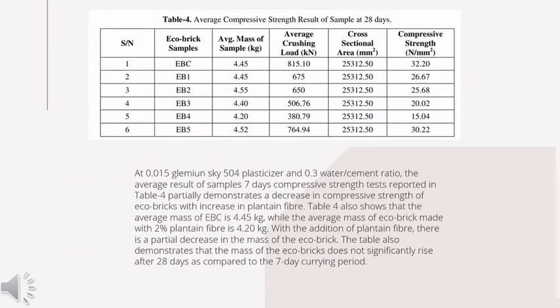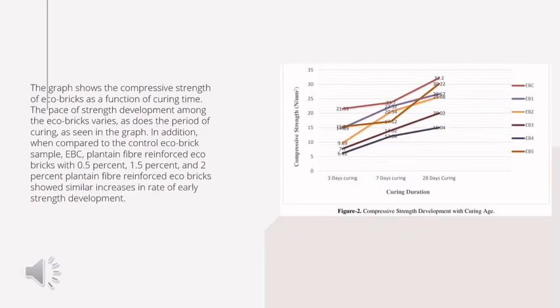For Table 4, at 0.015 Glenium Sky 504 plasticizer and 0.3 water/cement ratio, the average result of the 7-day compressive strength test reported in Table 4 partially demonstrates a decrease in compressive strength of the ecobrick with increase in plantain fiber. Table 4 also shows that the average mass of EBC is 4.45 kg, while the average mass of ecobrick made with 2% plantain fiber is 4.20 kg. With the addition of the plantain fiber, there is a partial decrease in the mass of the ecobrick. The graph shows that the compressive strength of ecobrick is a function of curing time. The pace of strength development among the ecobricks varies with the period of curing, as seen in the graph. In addition, when compared to the control ecobrick sample EBC, plantain fiber reinforced ecobricks with 0.5%, 1.5%, and 2% plantain fiber show a similar increase in rate of early strength development.